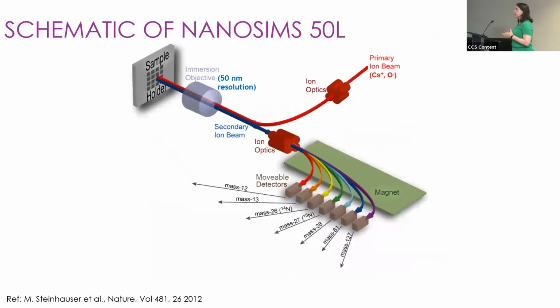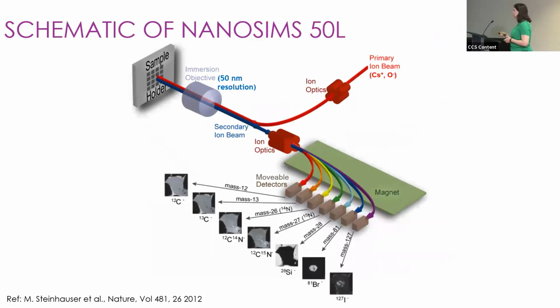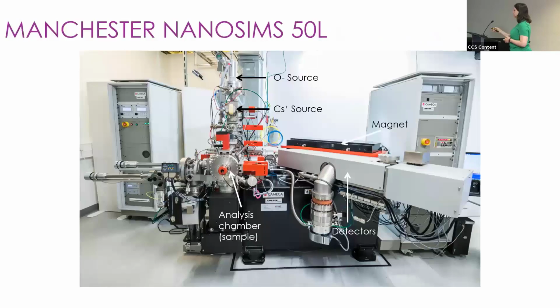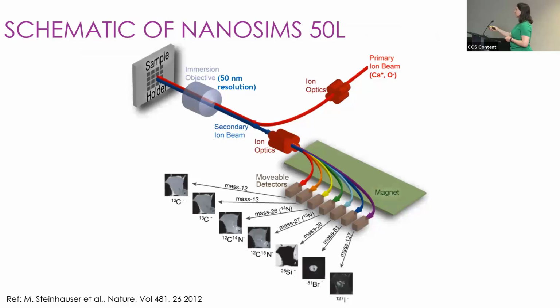So this is just a very simple schematic of the NanoSIMS instrument. We have two ion beams on the sample surface: a cesium ion beam and an oxygen ion beam, which we focus down onto our sample. We scan the ion beam over the sample, and we collect the secondary ions that come off the sample surface. In the NanoSIMS, we send them into a magnetic field, which allows us to separate out those ions according to their mass. From that, we can then build up chemical images of our sample surface.